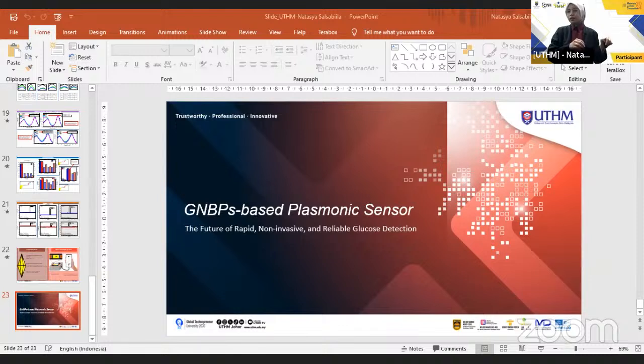And when we talk about thiol, it's a bit similar. When we functionalize the surface of gold nanobipyramids using thiol groups for too long, it can cause an agglomeration phenomenon, which also decreases the sensitivity response. But when we functionalize using thiol groups for too short a time, it also cannot increase the sensitivity, because the thiol groups cannot properly attach to the surface of the gold nanobipyramids. So what I would like to say is that the optimum time is very important, because both over and under can cause a decrease in the sensitivity performance. That's all.